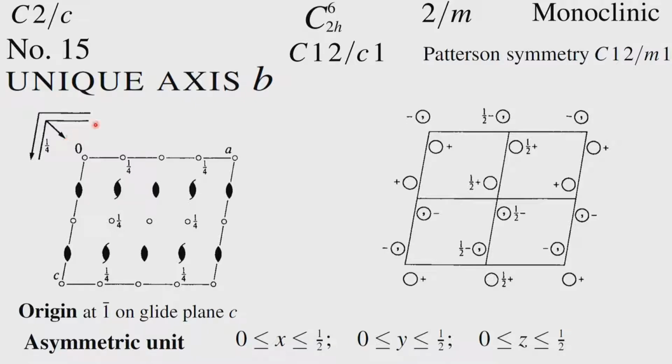We talked about the n glides, and this n glide will develop in the case we have a C2/c symmetry, and n glide, as you remember, will add not just half to one of the directions where we are now considering. For example, if you consider the glide plane associated with this origin, this is C and that is A. So, the translation symmetry that will be associated with the n glide will be half along C and half along A.